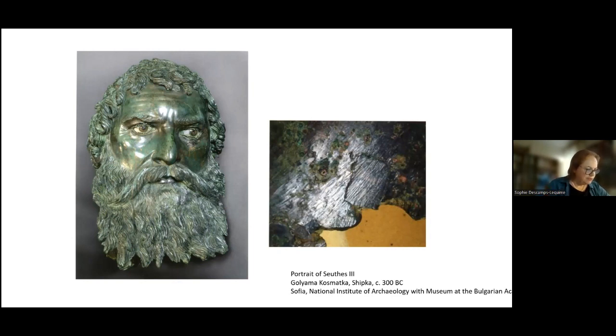As a result, the protective layer changed little before burial. This is what you see here. It is very thin and does not conceal, at the base of the neck on the right, the underlying traces left on the bronze by its original polishing. This thin translucent film was not intended to alter the bronze's rather pinkish incarnation, between 6 to 9% tin, but rather to enhance the realism of the epidermis.